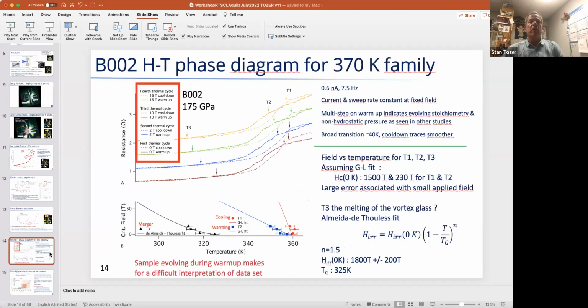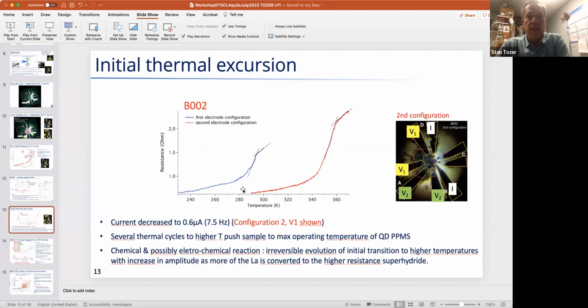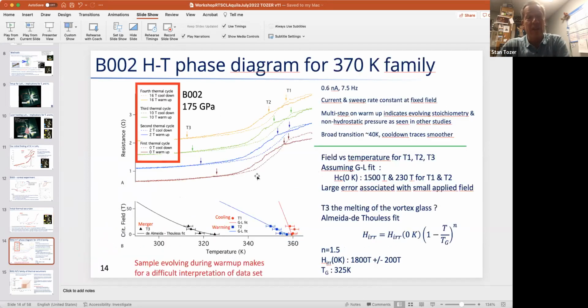And then if we apply, in that last curve, I'm sorry, go back here. If we look at this one and apply magnetic field, we can see a very, very subtle and almost non-existent shift in the cooling trace, which are the dotted lines. And in the warming trace, we do see a suppression of the field. And then for the third point of interest that we picked, essentially where the cool down and warm up traces converge, we see something that looks possibly like the melting of a vortex glass. The fit does not fit GL whatsoever.